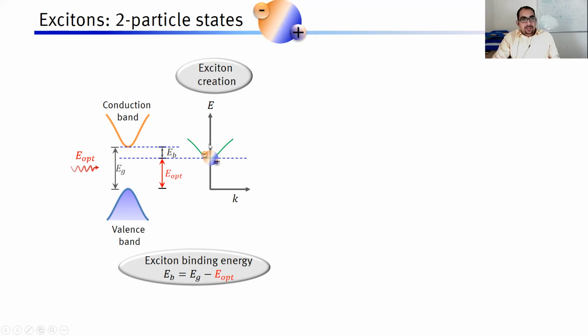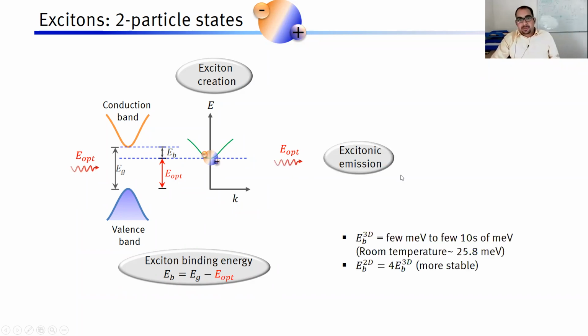And this Coulomb interaction energy will reduce the energy of this transition, because this is a bound state now. And this exciton will appear as a sharp resonance below the band gap, below the actual band gap. Actual band gap is EG. We can call this the optical band gap, E optical, where the exciton starts to absorb. Okay, so binding energy is then the normal band gap, which is the single particle band gap, minus the optical band gap. And then this exciton can recombine and give rise to a sharp line in the emission spectrum as well.